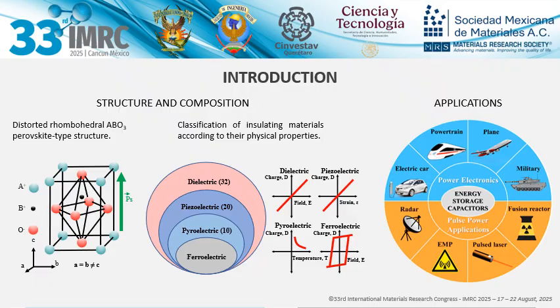To overcome these limitations, a common strategy is ionic doping, partially substituting A-site or B-site cations in the perovskite lattice. In our case, we chose to dope with 6% aluminum, a cation with a smaller ionic radius than iron, aiming to improve structural stability and functional properties without altering the overall valence of the system.